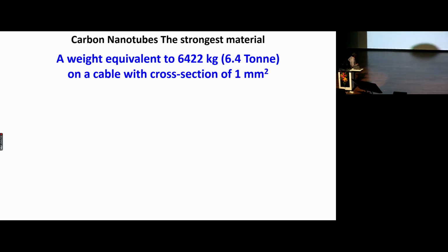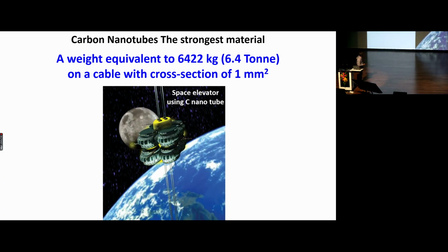For example, if we talk about the strength of this carbon nanotube, the nanotube that I showed, it's one of the strongest materials that we know of. If you could make a nanotube cable of 1 square millimeter cross section, which is a very small cross section, you can hang from it 6.4 tons of weight. So you can use a 1 square millimeter cable to lift up 6.4 tons of weight, which is absolutely amazing. There's nothing that can be stronger than that. In fact, this also almost makes one think that we can realize one day what Arthur C.